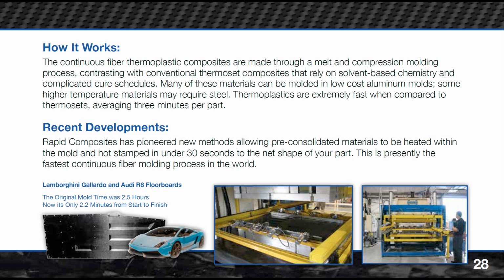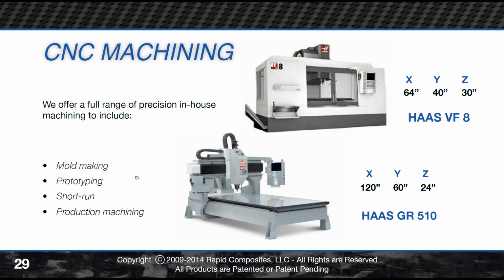We work with their ACSL, Advanced Composite Structures Laboratory, and we've been the behind-the-scenes partner on their thermoplastic work that they're going to be putting on their next-gen vehicles. When they came to us for the Gallardo and the R8, which is basically the same car, looks different externally, but internally the chassis and drivetrain are identical, the floorboards were being produced in 2.5 hours by their fastest vendor, using an autoclave approach. With this shuttle system, heater system and press configuration, we took it from 2.5 hours to 2.2 minutes per part. So it's a very fast process.